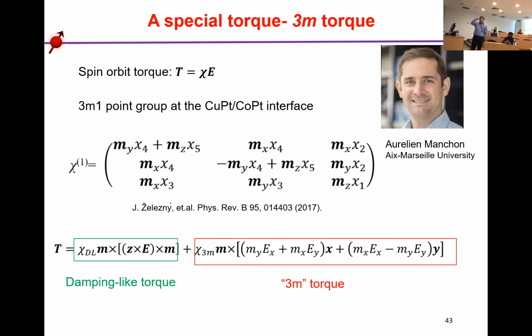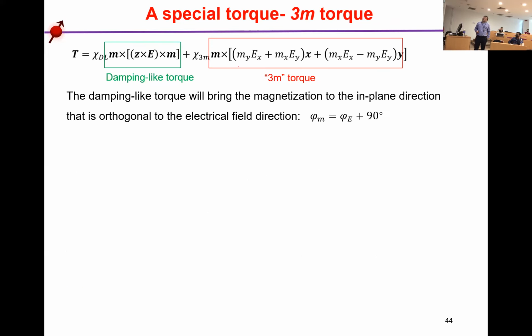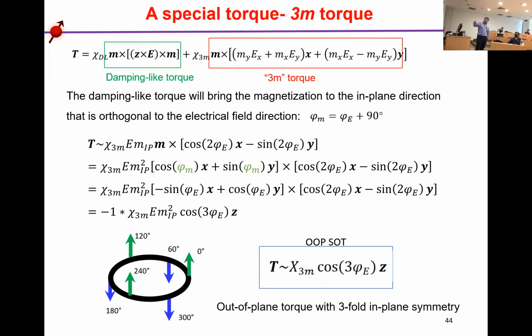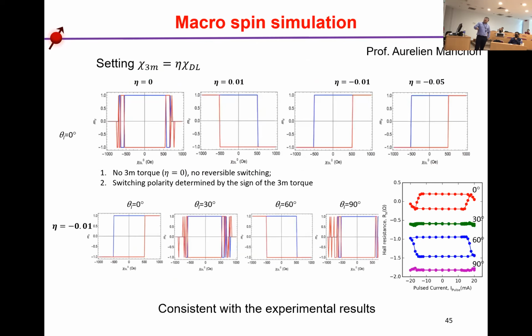But for the 3m torque, we can see that if the magnetization is perfectly in the z direction, my and mx are 0, so the 3m torque becomes 0. So actually we understand this scenario. The damping-like torque will switch the magnetization along the y direction, and then the 3m torque starts to work. So based on this, we substitute phi_m equal to phi plus 90 degrees, because the magnetization is always 90 degrees different from the electric field. From here we get that this torque has threefold symmetry. We have also done macrospin simulations which are consistent with our experimental results.